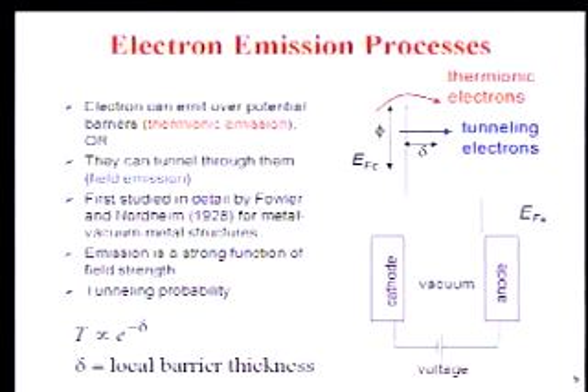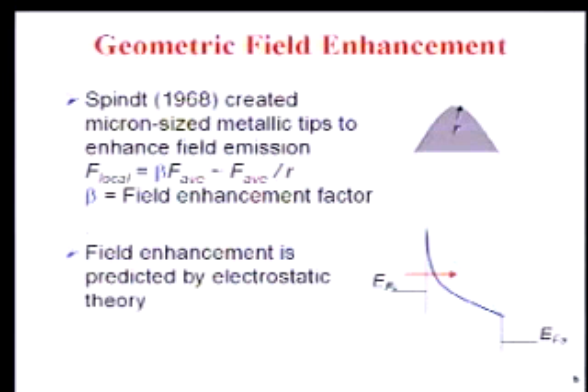One thing to note is that the tunneling probability is a very strong function of that barrier width. And so if we can play around with the barrier width, then we might be able to filter the energy a little bit better. One way that we can change the barrier width is by going to very small emitter materials. And back in 1968, Spindt did this and made Spindt emitters, where essentially if you make this radius of the emitter around 10 nanometers, you get a very profound increase in the electron emission. And the reason for that is that you took what was a linear field, a linear potential profile between the cathode and the anode, and you concentrated the field near the source of electrons and allowed them to tunnel out.